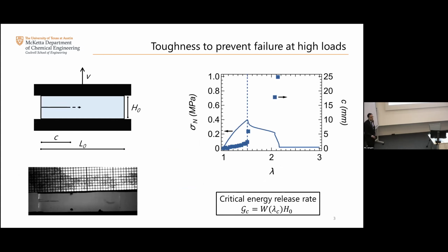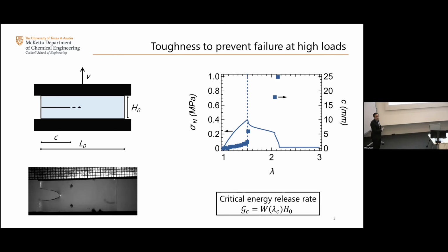So because they can sustain large deformations, for a long time, really, the fracture mechanics community and the polymer community have really thought about how do you actually make these materials resistant to fracture. It's a pretty natural question to ask because you are going to apply a very large deformation and you don't want your material to break. And the typical experiment that you would conduct to characterize the fracture energy and the fracture toughness of this material is that you introduce a pre-crack, that you think about as a structural defect, into your system. And then you deform the material at a constant velocity. Here in the bottom, I have a video of how that would look. So you have a pre-crack in your specimen, your elastomer. And this is an experiment that I conducted in ESPCI that I will get to in a bit. And then you see your crack grow. And eventually you reach a point where the material fails catastrophically.